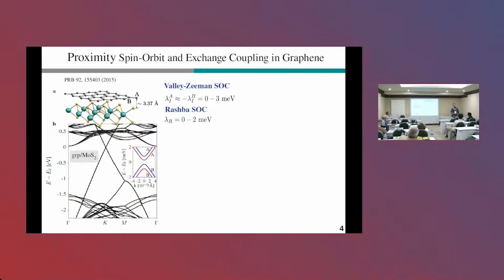Now, one of the spin interactions that can be induced in graphene is the proximity spin-orbit coupling, as we have already heard today. So, for example, if you consider graphene on top of a TMDC, in this particular case MoS2, and if you calculate the band structure from first principles, you will find that the two individual dispersions are very nicely preserved due to the weak van der Waals interaction of the monolayers. In particular, the Dirac cone is very nicely preserved within the band gap of the TMDC. However, if you then zoom in to the Dirac states, you will find such a splitting of the bands. And this splitting results from the proximity-induced spin-orbit coupling, which is of the valley-Zeeman and Rashba type.